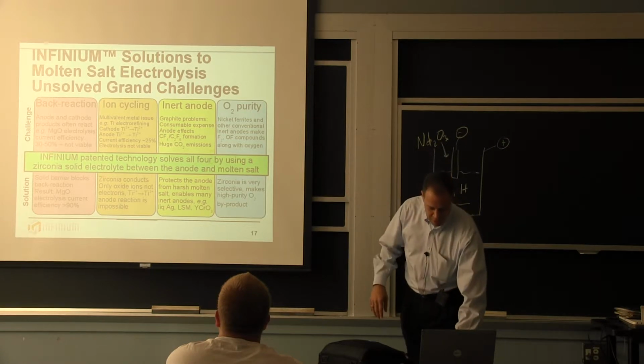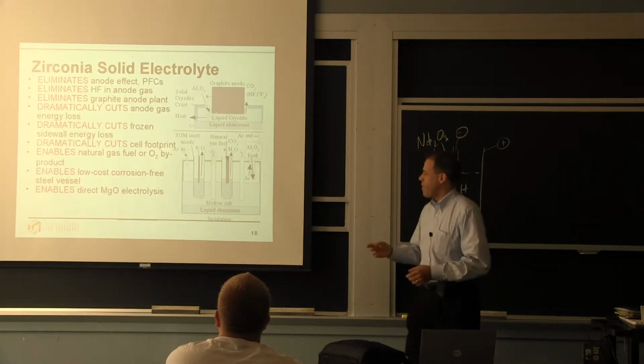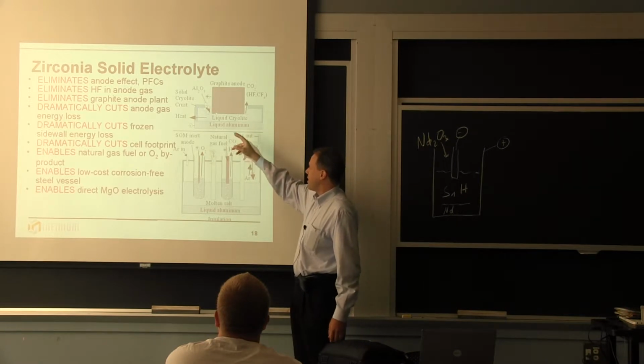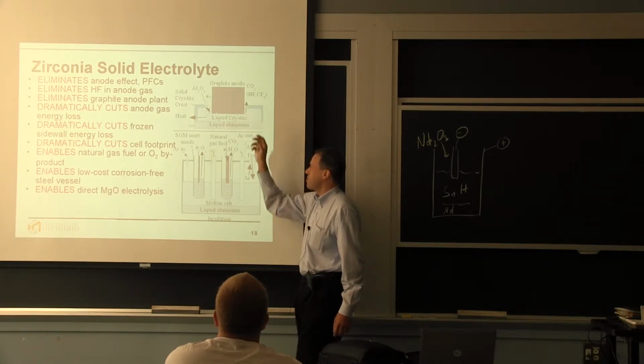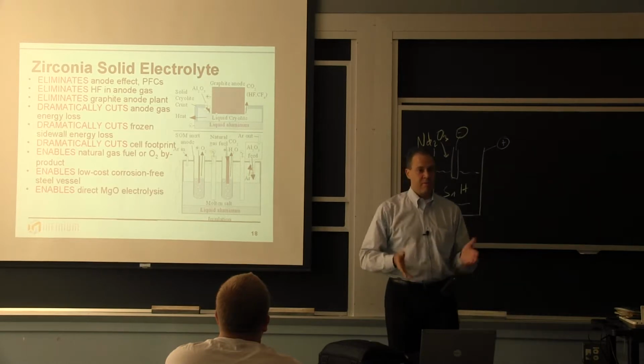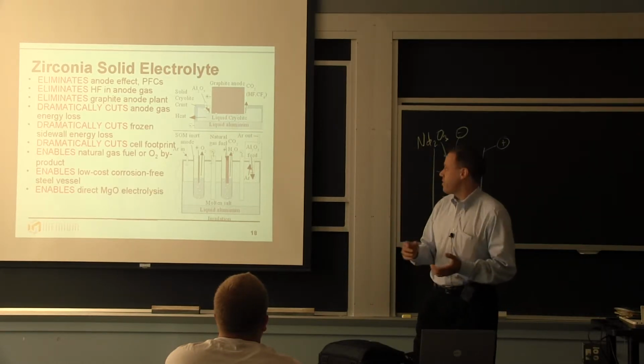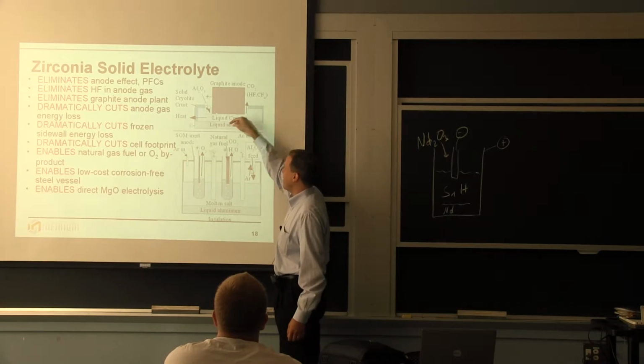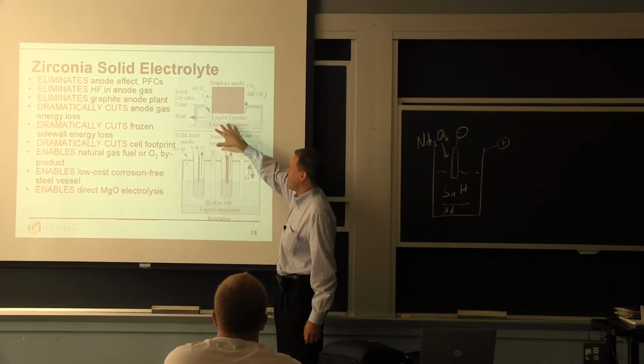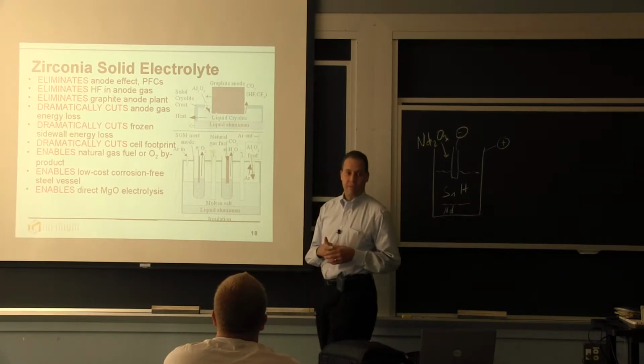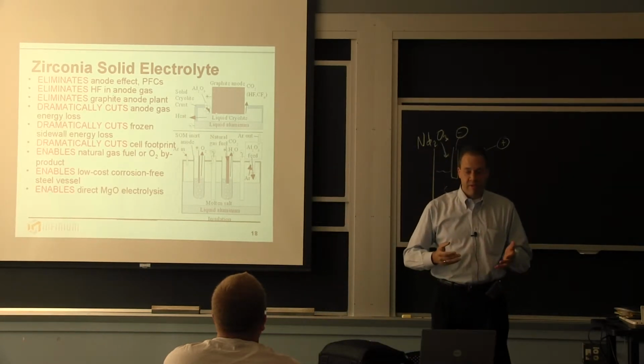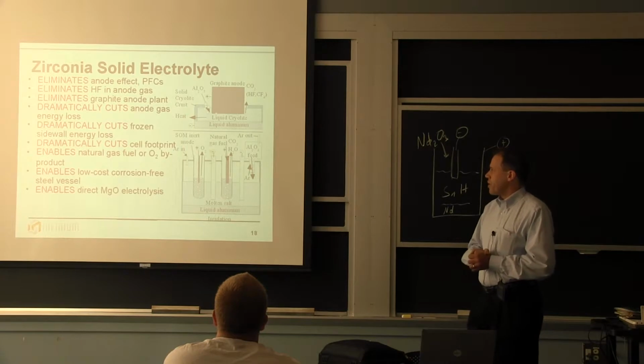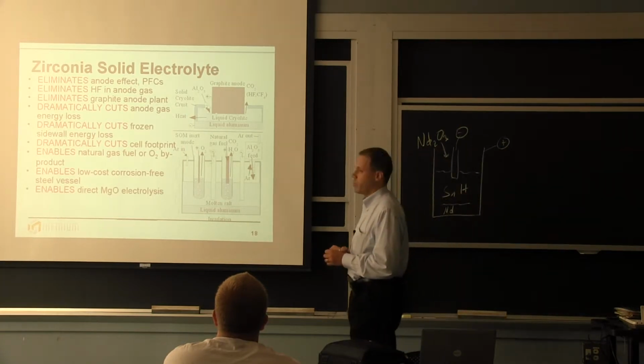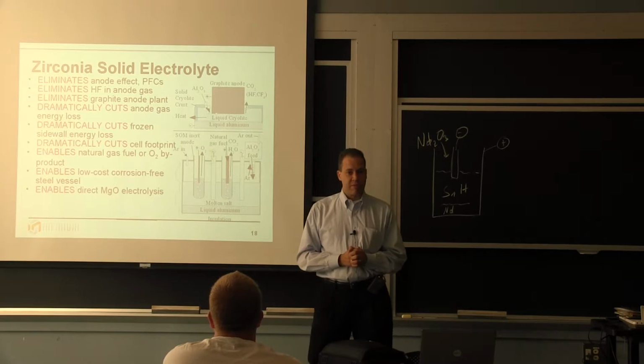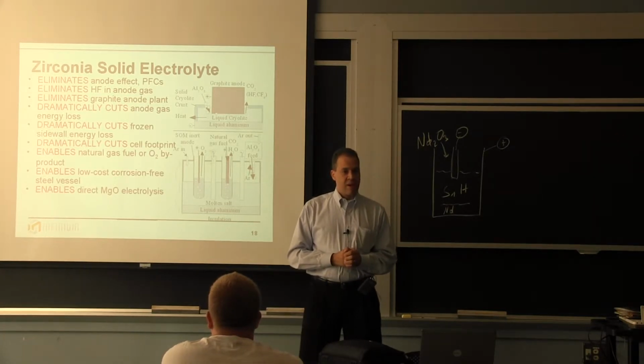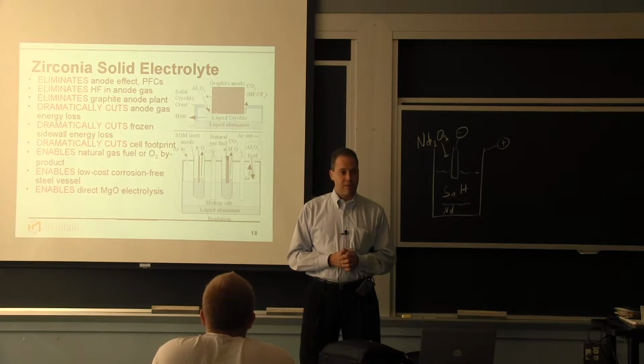Let me skip this for a moment. Basically, in a typical aluminum cell, the anode just sits in the molten salt, and you generate CO2 right there in the molten salt. You apply a potential, and so you produce liquid aluminum at the cathode. At the anode, the oxygen from the aluminum oxide reacts with the carbon. You produce CO2. But in addition, the alumina is not completely dry, and it picks up some moisture from the atmosphere. And when you have moisture at high temperature and fluoride salts, you make some HF.